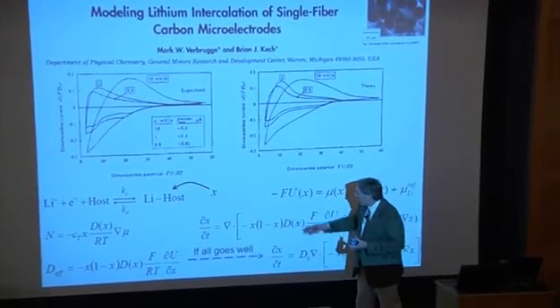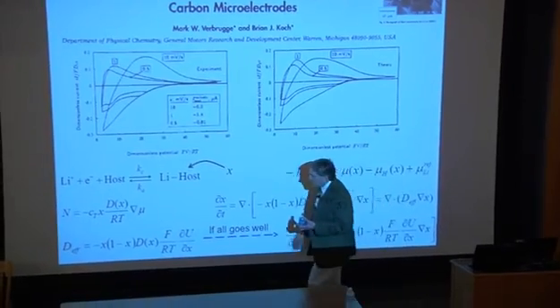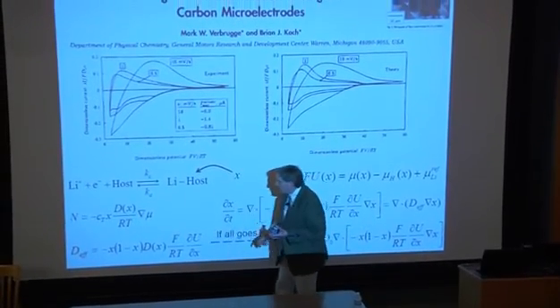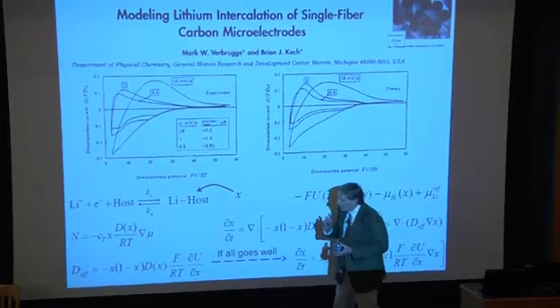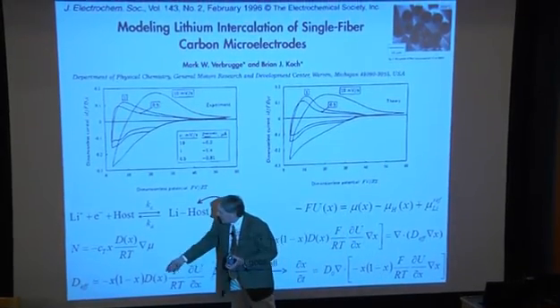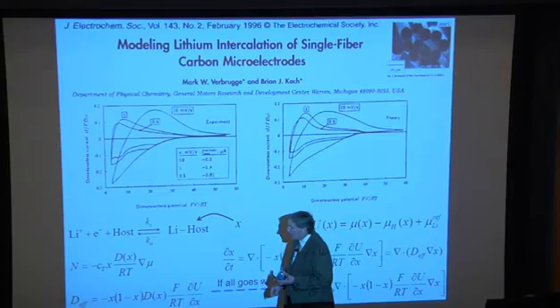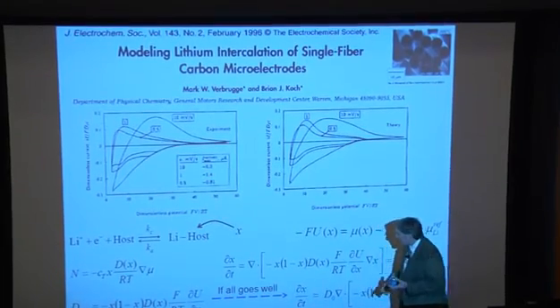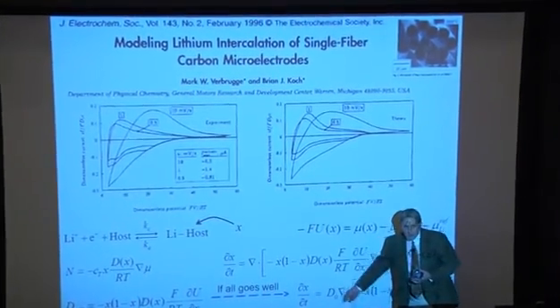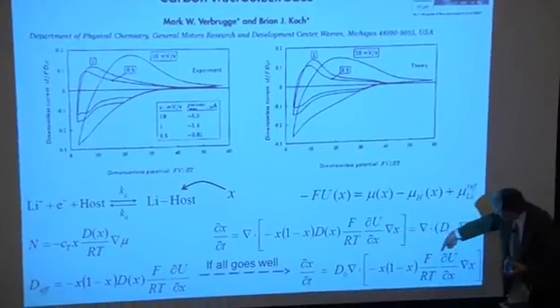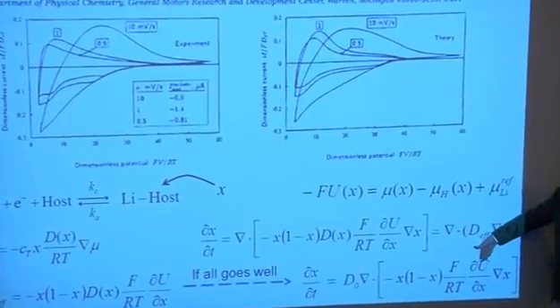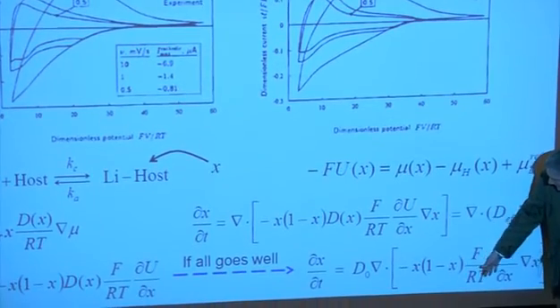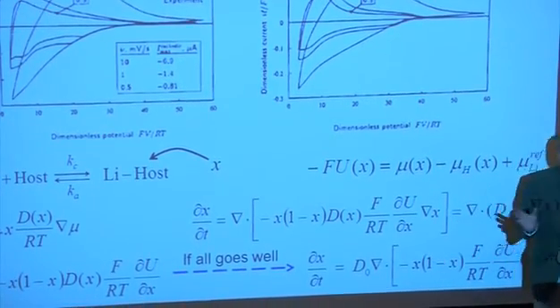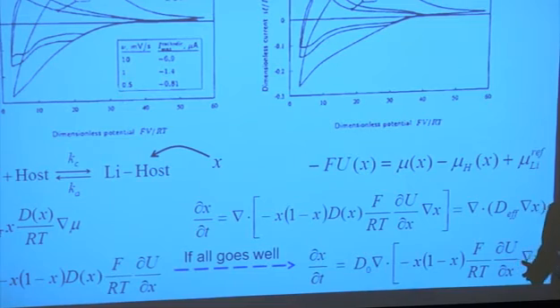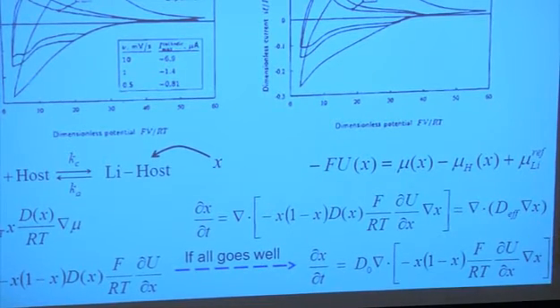Now, if all goes well, this whole effective diffusion coefficient, which I've written down here, simplifies, when you're at infinitely dilute systems, the activity coefficients that come into these expressions go to unity. You get Fick's law. So infinitely dilute, you get the infinite dilute diffusion coefficient. And then everything else inside of here is easily computed. This comes from the open circuit potential, Faraday's constant over gas constant and temperature, mole fraction of lithium. It's nonlinear, but everything is available to you. You don't have to introduce any new information. And that worked quite well in this single phase system.